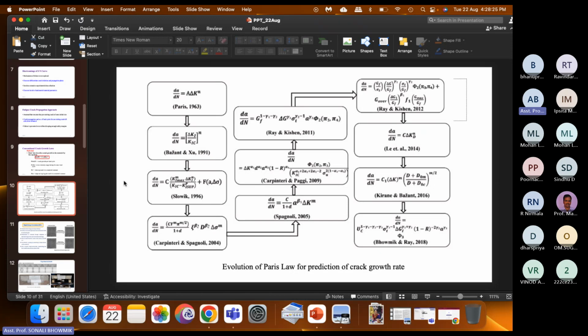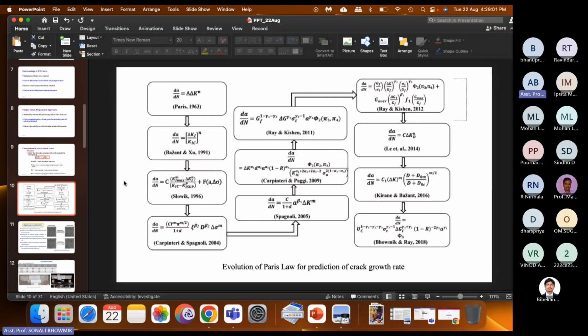Now here there are a few things. This type of model is only limited to plain concrete, where there is no embedded reinforcement. When you are talking about reinforcement, many more things come into the picture: strain difference between reinforcement and concrete, bond force, corrosion, everything comes into that scenario. So the future aspect for the analytical area to predict the fatigue crack growth of concrete is to develop a much improved model which can clearly predict the fatigue crack growth rate of reinforced concrete. But the critical areas I have just mentioned, corrosion, environmental aspects, durability, all those things need to be considered.